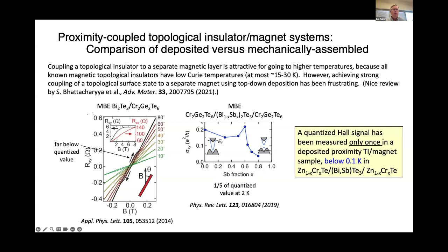In the graphs here, I show you some of the previous attempts using the same magnet that we're using in our experiments, chromium germanium telluride. It's a van der Waals magnet. You'll see Jason Petta's group measured resistance changes of less than 1/10 of an ohm, which is way less than a quantized value. Tokura's group, having magnets above and below, only found quantization about 1/5 of the quantized value at 2 Kelvin. And I'll speculate near the end about why things are difficult with the positive samples.